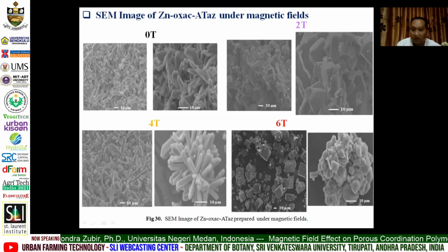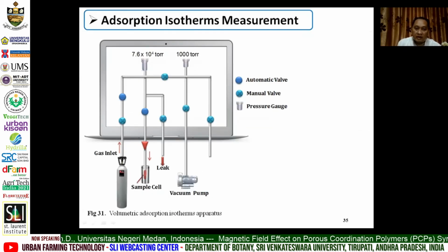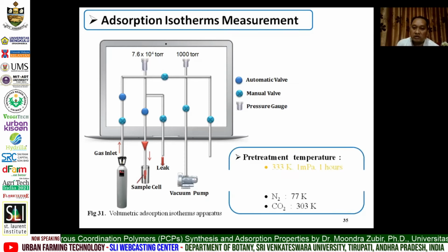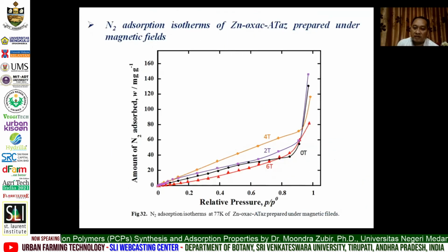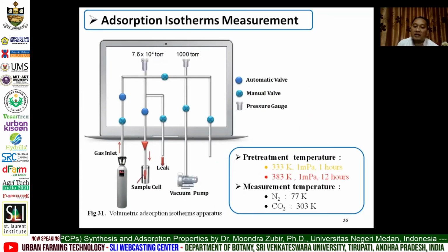And this is the adsorption isotherm measurement, the same system used for the adsorption isotherm with the previous PCP. We use the volumetric adsorption isotherm method, and we do the pre-treatment temperature with the same stages: an initial stage at 333 Kelvin for 1 hour, and then 383 Kelvin for 12 hours. Nitrogen adsorption is measured at 77 Kelvin, and carbon dioxide at 303 Kelvin.